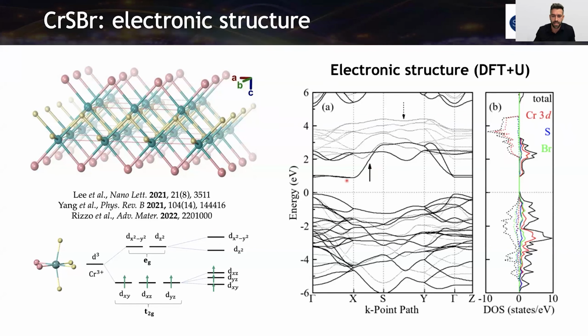Of course, we can see 2 things here. The one is the anisotropy of the crystal that makes that from gamma to X, that is parallel in real space to the A axis, we have no dispersion here in the conduction band, whereas from gamma to Y, this is very dispersive. So the material behaves kind of like a 1D electronic system. And if we take into account the projected density of states, we can observe here these spin up t2g orbitals that are filled, we have the eg spin up empty, and of course, all the down components are empty.